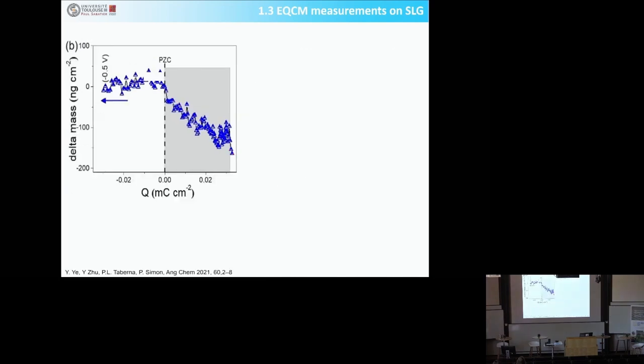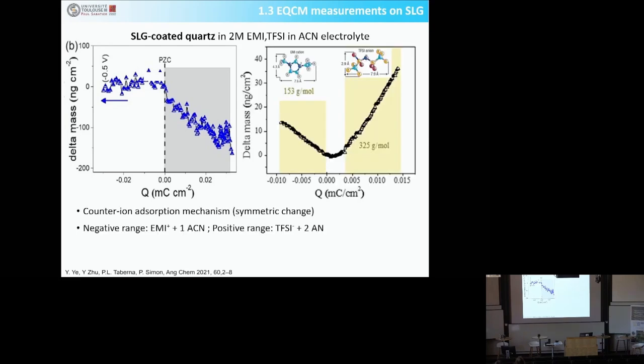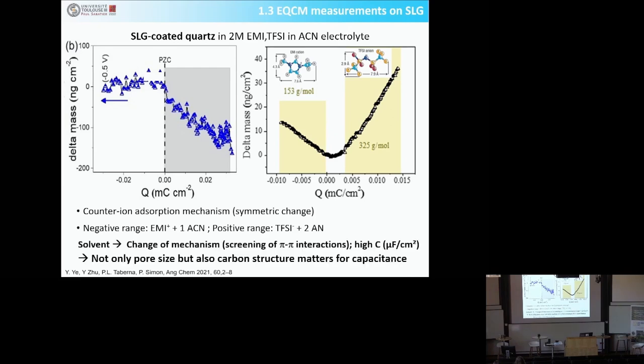When you inject electrons into the graphene, the cations simply reorient to balance the charge injected into the graphene. This is the first example of charge storage just by electrolyte organization — simply changing the orientation of cations on the surface without any ion flux — which means you locally change the dielectric constant of the electrolyte. This is very important: if you control the PZC of your material, you can have a charge storage mechanism without any net ion flux onto your electrode.